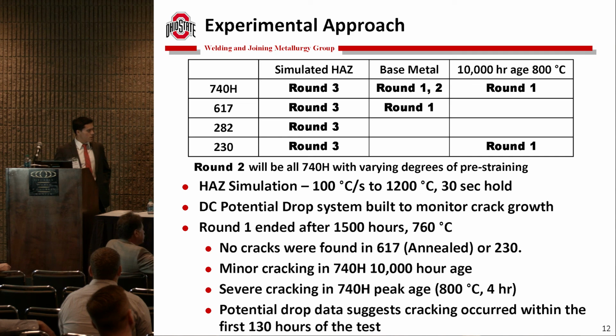So round one, which I'm going to discuss the results of real soon, was simply to look at a range of microstructural conditions. First of all, to make sure that there would be cracking, and hopefully this cracking will correspond with the right microstructure. Based on the results of round one, I determined that I need to take a step back with round two and look at the various degrees of pre-straining, maybe not pre-strain as much, or try to slow down the cracking I observed. See, the heat-affected zone simulation will be done like this. I've been trying to build a potential drop system to monitor crack growth, so I'll explain that really briefly. And what I'm mostly going to talk about are the results of this first round one test.